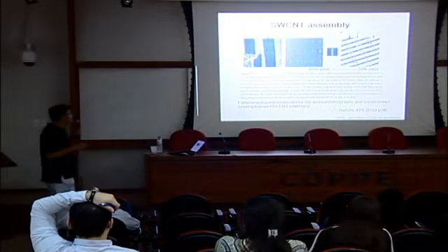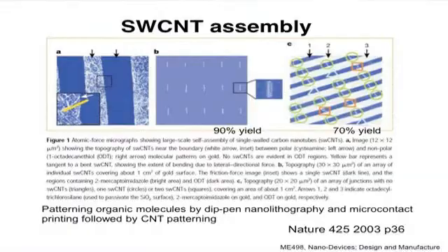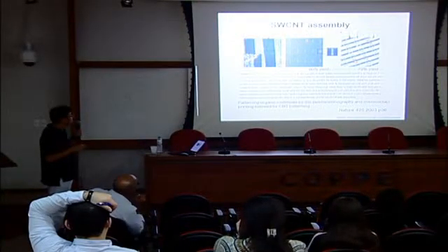to be positive, right? So if you try about 10 of these electrodes, you will get a success of maybe 5 or 6. Okay? That's the rough idea. And in this case, a similar thing happened. They partially removed the oxide surface, which was positively charged, and then negatively charged nanotubes were aligned out there.